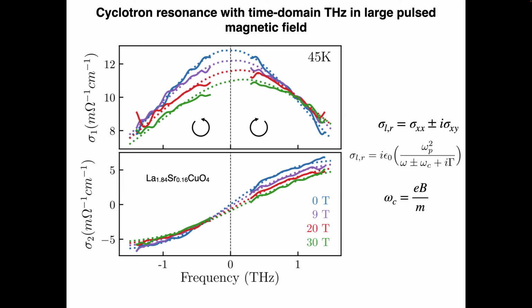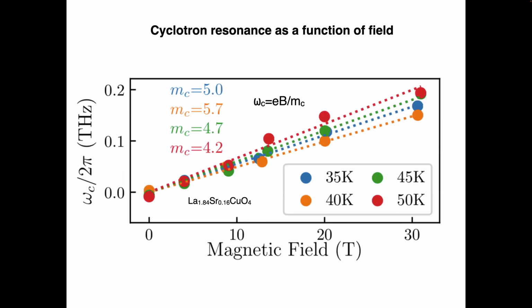We don't measure near zero here very well, but we can see from looking at the real part, positive and negative, and the imaginary part, positive and negative, we can fit and pull out the cyclotron resonance to really high precision, and one gets interesting information out of that. This is how those peaks go, and that's the cyclotron resonance frequency as a function of magnetic field.